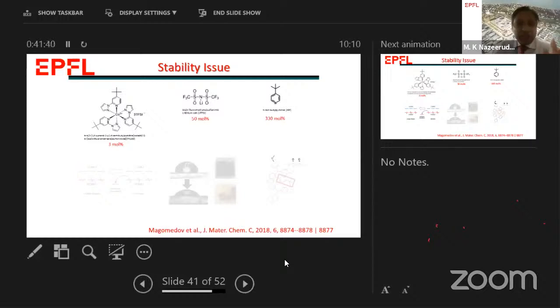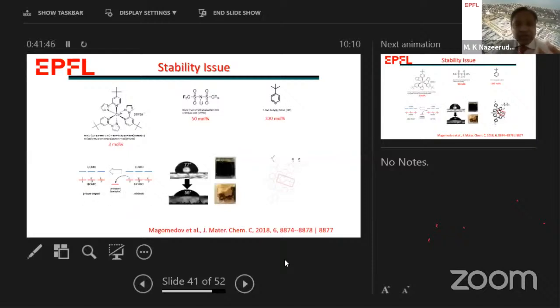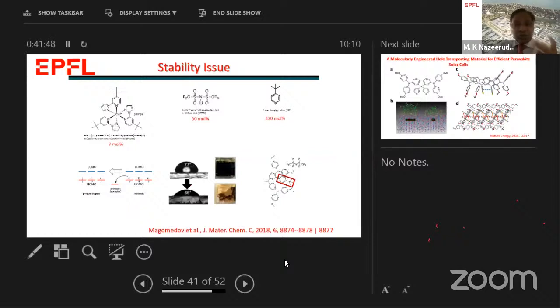Next, click on next again. Click once again, please. Yes. So using this type of dopants, we take the intrinsic material and remove one electron from the hole transporting material, and then this becomes an extremely mobile molecule, a conducting material. But as a result of these additives, if you look at the contact angle measurements, without any dopants the contact angle is 77. With dopants, the contact angle is decreasing. So that means it's becoming hydrophilic.